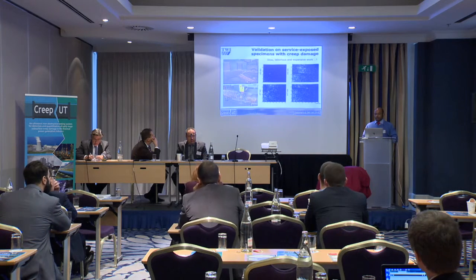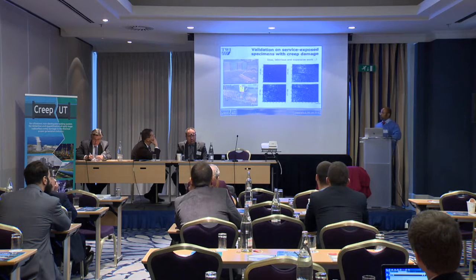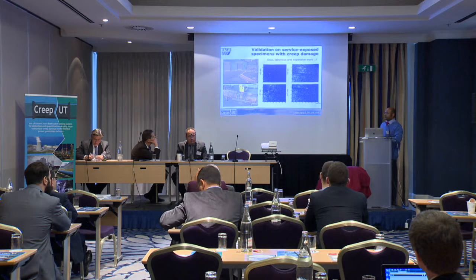And during the CreepUT project, SSE also started providing specimens, that's Ferrybridge C in the background, which is a very important power station for our work. They started providing specimens which had been in service, and you can see a number of specimens in the holding yard, which then come to TWI to be replicated across the weld.